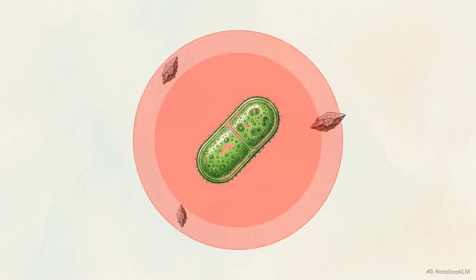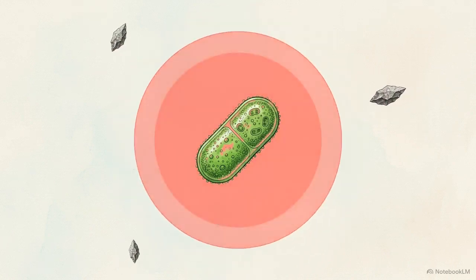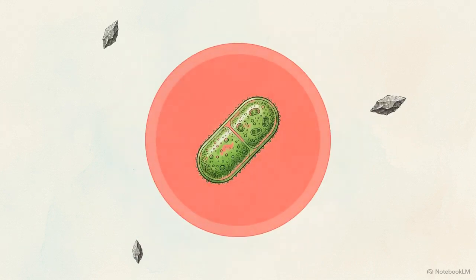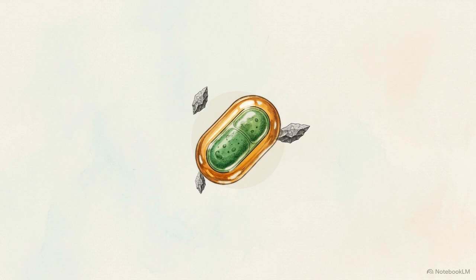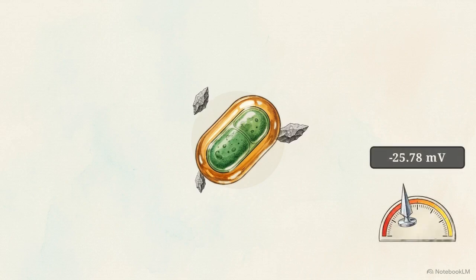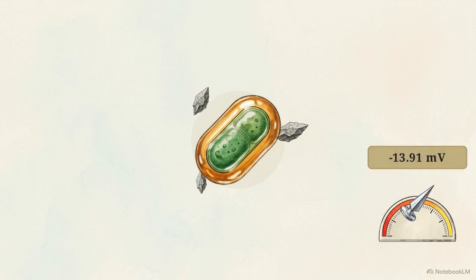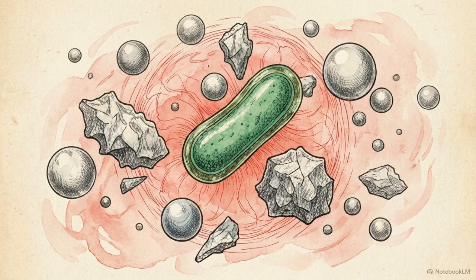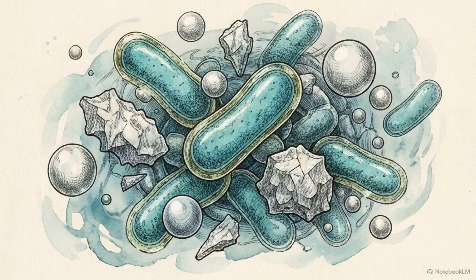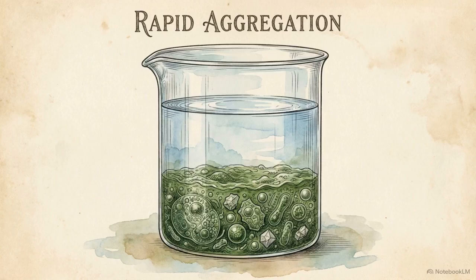Wild-type cyanobacteria possess a highly negative charge in their outer layer. This negative electrostatic field naturally repels suspended plastics. Limonene secretion suppresses that charge. The zeta potential drops from negative 25.78 millivolts in wild-type cells to negative 13.91 millivolts in the HCC strain. Reducing this negative surface charge weakens the electrostatic repulsion. This exact thermodynamic shift allows the innate hydrophobic attraction of both the limonene and the plastics to take over, causing them to rapidly cluster. Operating with this engineered surface chemistry, the HCC strain removes 91.4% of polystyrene microplastics from a solution in exactly 1 hour.